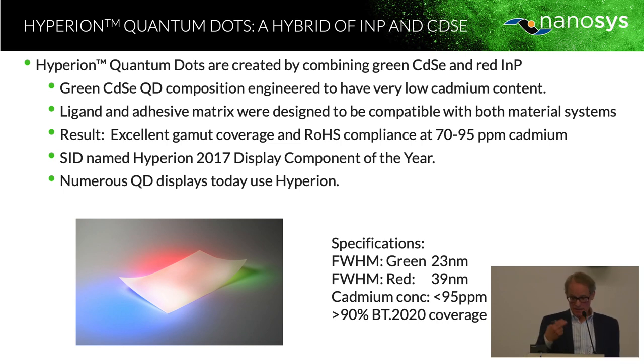In terms of reaching high color gamut, and with the idea that you may not be able to have higher levels of cadmium in displays, Nanosys scientists a few years ago created what we call Hyperion, which is basically a hybrid material. What scientists did was engineer a very low cadmium green emitter that had very narrow full width half max, and combined it with a cadmium-free red emitter, which is much broader. But it turns out that it's more important for green to be narrow than red because it's the one that's between two color channels. And so what they were able to achieve is very high, over 90% gamut coverage with this material and still remain under the 100 ppm cadmium level. So far this is not terribly important because cadmium is exempted and can be at higher levels, but if that exemption goes away, this will become one way to still achieve higher product gamut.